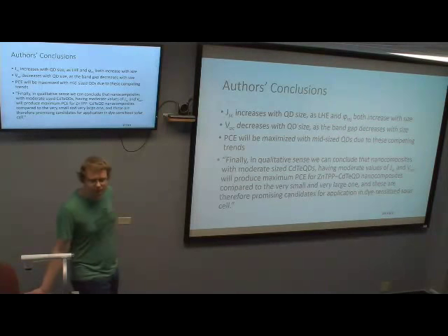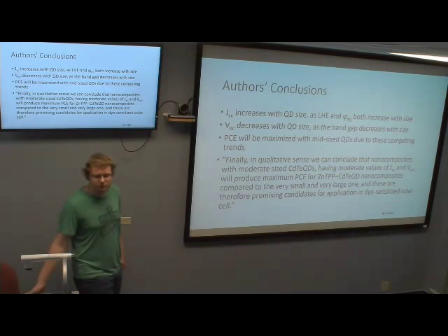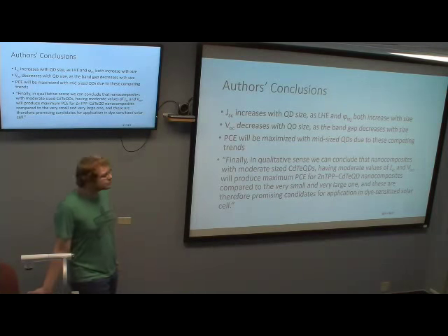Or it's just the alignment of your LUMO orbitals with respect to the HOMO-LUMO gap. They're not fixed, they're also moving when you change the size, which is possible to imagine because when you increase the size of the quantum dot, the surface dipole moment is also changing. And you probably decrease the static dipole moment of the surface, especially if you go to really large sizes.